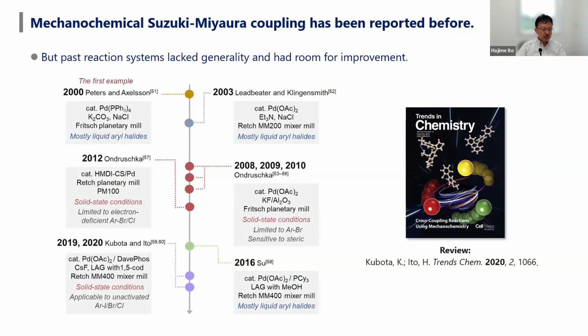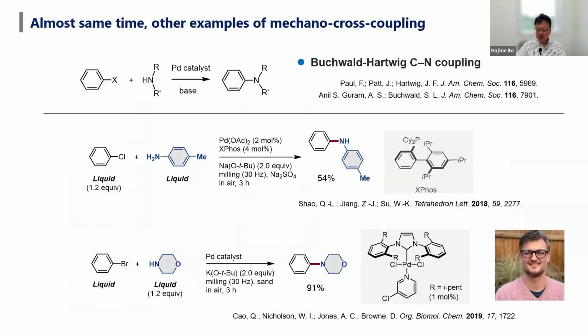We also tried to find good reaction conditions for Suzuki coupling. In 2000, Peters and Axelsson first published an example of cross-coupling under ball milling reaction conditions, and other people also reported several examples. But honestly speaking, the reaction was not so general and not so useful for many substrates, so we decided to find better reaction conditions. Around the same time, Professor Su in China and Professor Browne in the UK also reported palladium-catalyzed cross-coupling reactions under ball milling conditions.